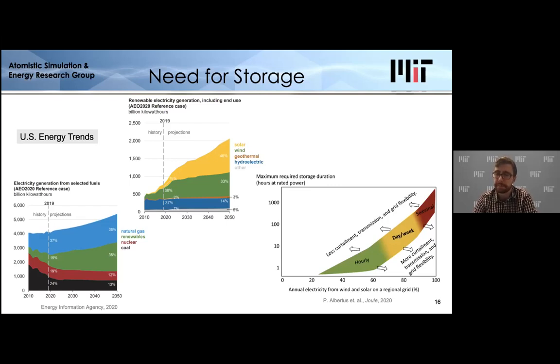So this plot on the bottom right, there have been a number of academic studies looking into how much storage we will actually need. And the important numbers to look at is on the x-axis, we have basically what percent of the grid is provided by solar and wind. And the y-axis is the storage duration, or basically how many hours of backup power do we need if that percentage of our grid is solar and wind. So you can see there's sort of this ideal band that indicates the duration of storage necessary for a stable grid with high penetrations of renewables. So something like 70 or 80% penetrations of renewables, which is reasonably possible in the near future, still requires tens to hundreds of hours of storage to account for seasonal, not so much seasonal actually, more like daily or weekly variations in power.